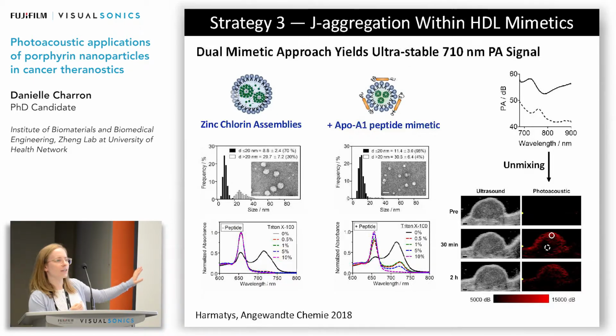So one advantage of this system is that it has very intense photoacoustic contrast compared to a lot of what we've created before because of this very dense dye packing. And you can even see that in the TEM images, how much smaller these particles are with this apoprotein mimetic structure. So we did photoacoustic imaging just in a subcutaneous model, and these are unmixed images, so we can see the probe along the outside, the rim of the tumor where it's oxygenated, and not in the deoxygenated avascular core.